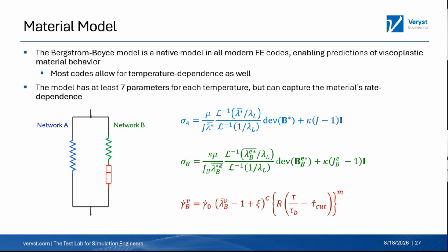And we've got another couple of parameters there. 1, 2, 3, depending on how you count. 1, 2, 3, 4, 5, 6, 7. Which is a little much because some of those we actually end up fixing. Tau hat cut is usually fixed. Gamma dot 0 I fix as well. So really we're looking at tau B, C, the Greek letter xi, and M to help us understand that. The power of that is that it gives us a time-dependent response that is non-linear. We have all these exponents here. That is non-linear and can capture the complex behavior of these materials.